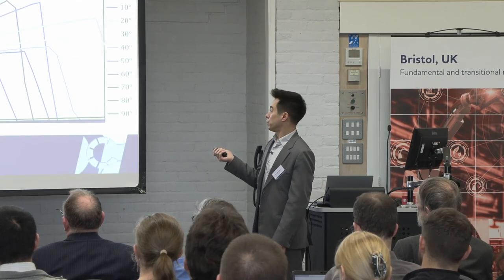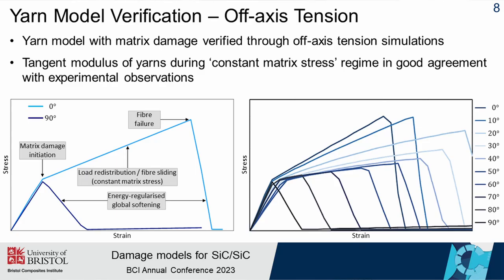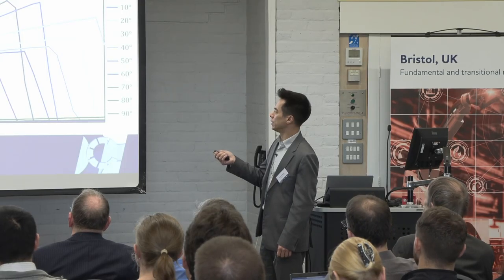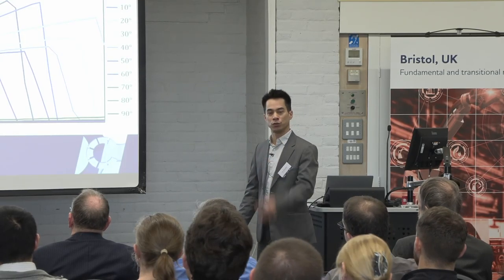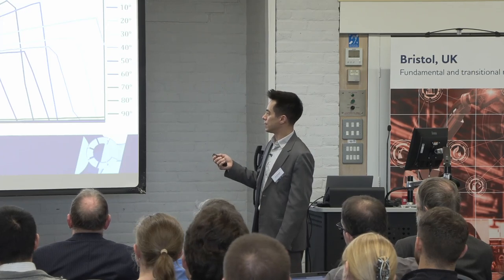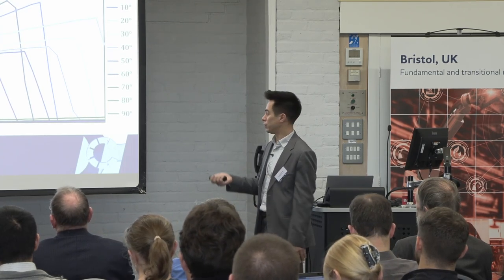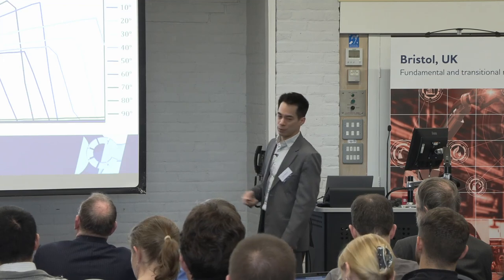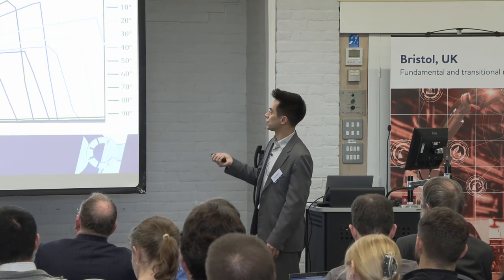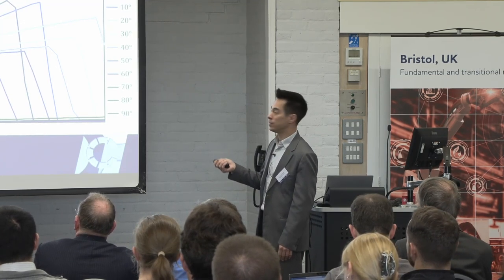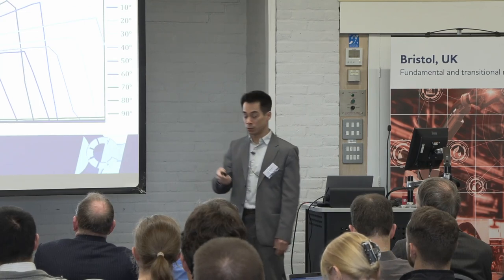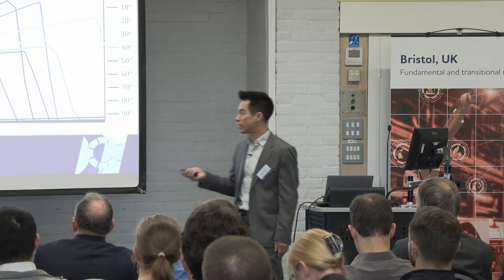And this is the result of this off-axis simulation, off-axis tension simulations, and you can see, highlighting here, what that constant stress assumption means. It actually means overall that there will be a tangent modulus to the composite as the damage develops. And this is the result of several off-axis tension tests. So you go from the very brittle case to the very pseudo-ductile case, depending on the direction of loading.